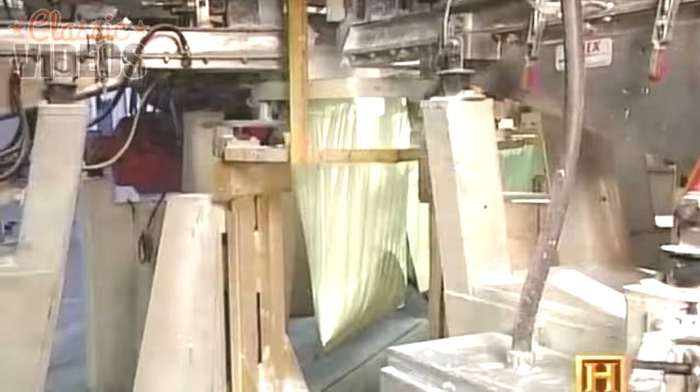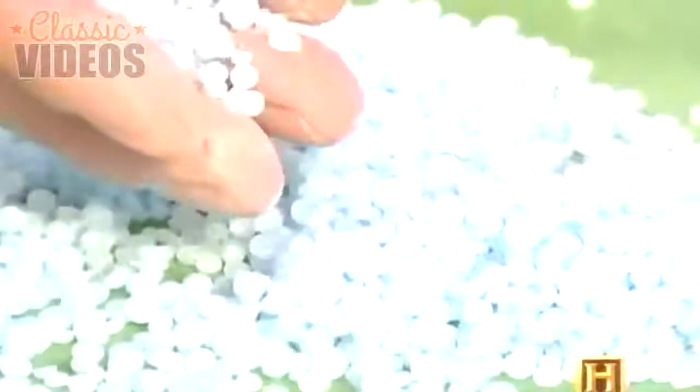Chemicals and additives are precisely mixed with rubber to the specifications of a recipe. These chemicals are weighed on the machine behind me to very precise weight tolerance. And just as an example, here you have an antioxidant, which protects the tire from attack by oxidation. This is a resin. It helps it to adhere to the metal. This product is a wax. It helps in the processing of the rubber and also helps the tire to stay black. This is another antioxidant. This product is an anti-ozone, so same purpose except this time to shield the tire from attack by ozone. You would have anywhere from 3 to sometimes up to 8 of these different chemicals in a given formulation, but when you add it all together, it would only represent 3 or 4 total percent of the weight of the rubber compound.